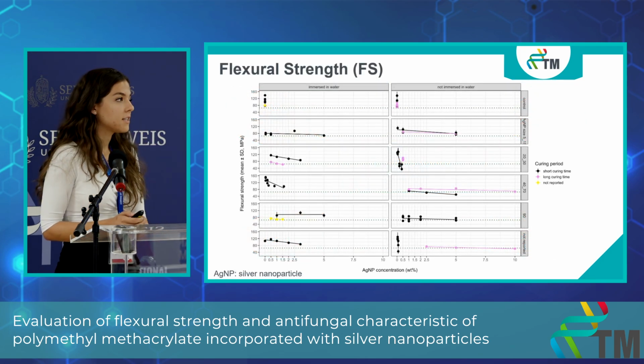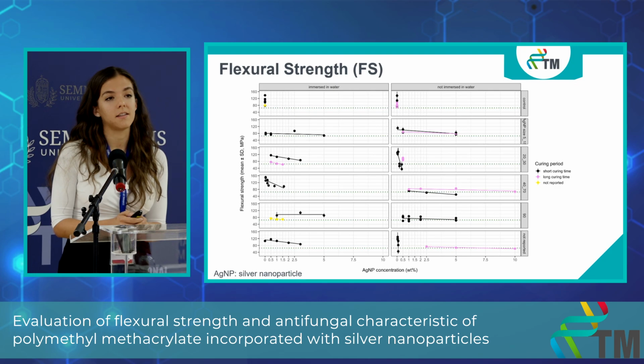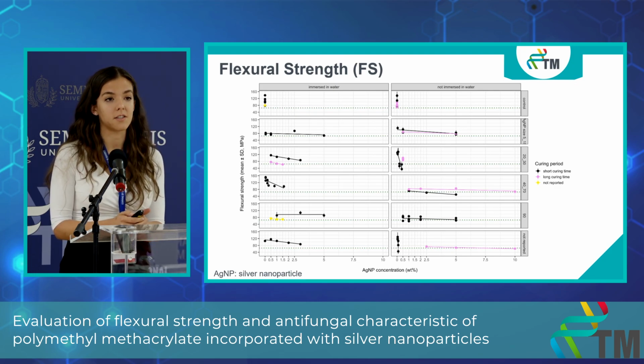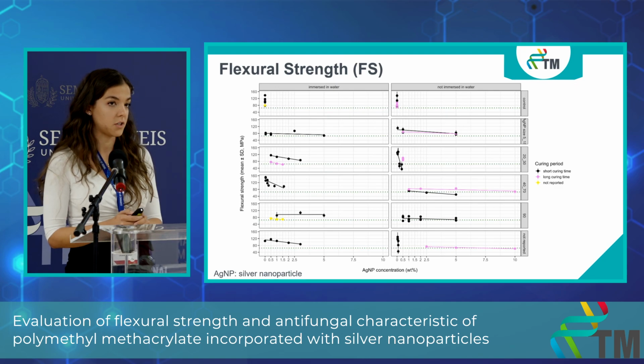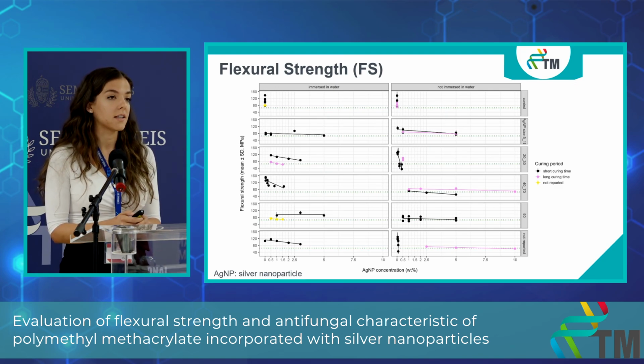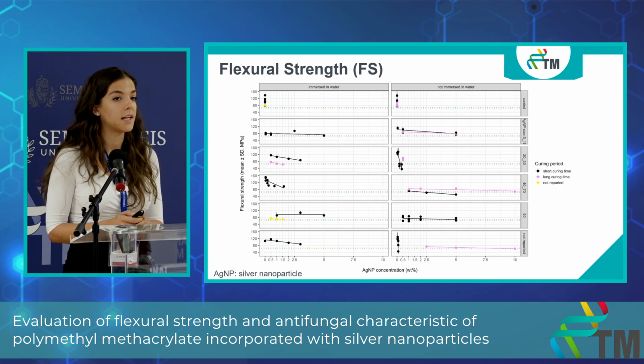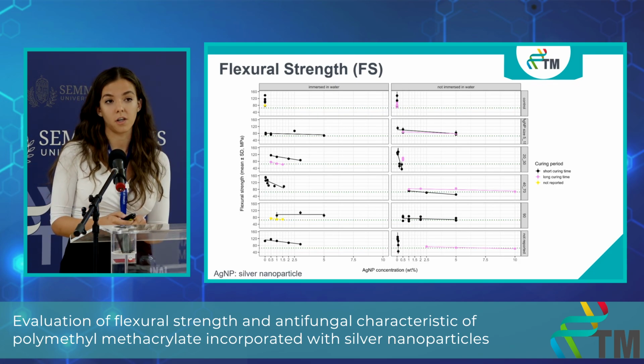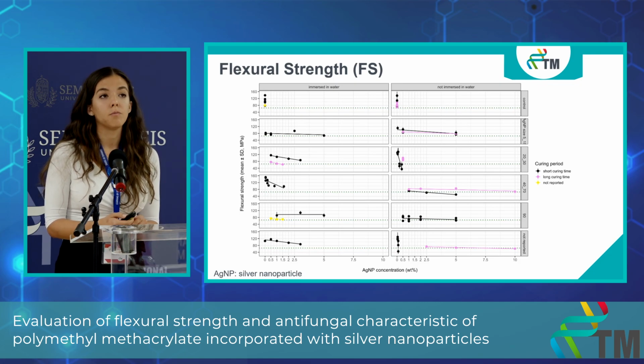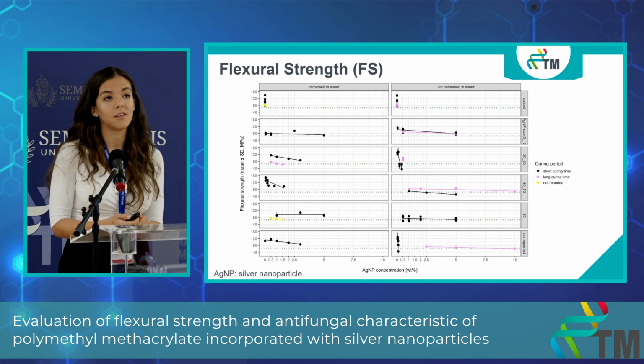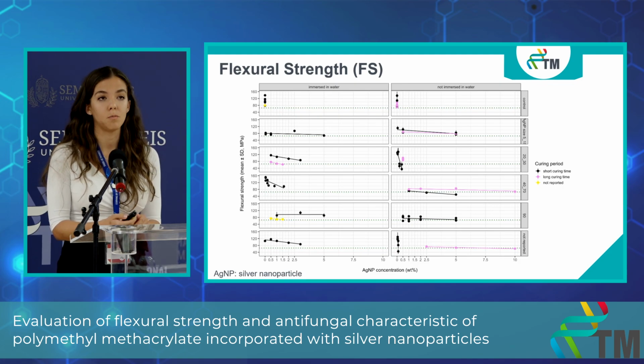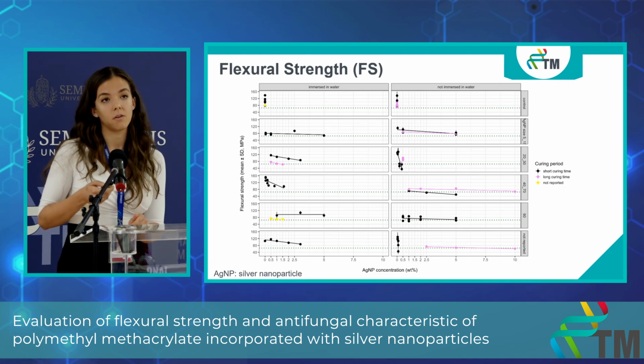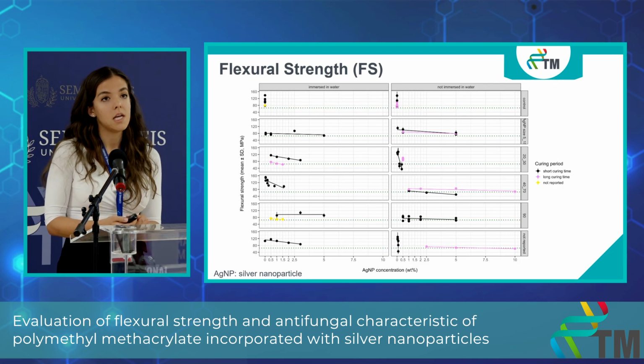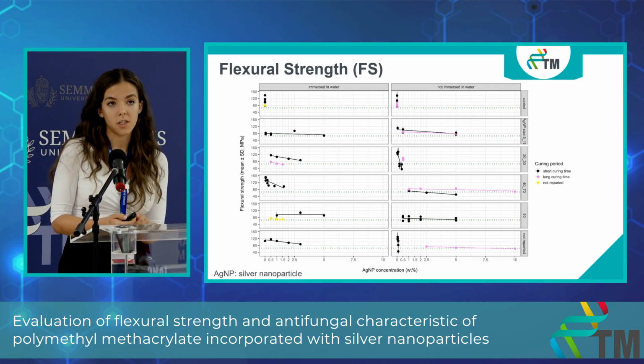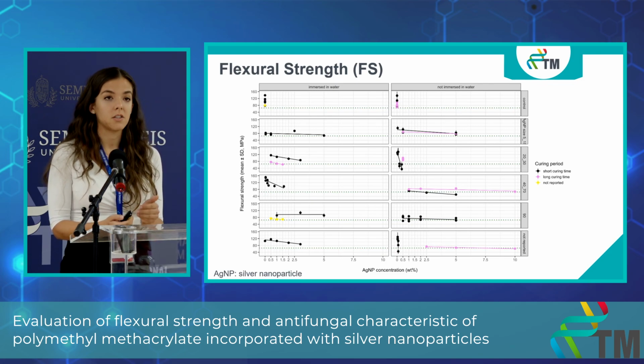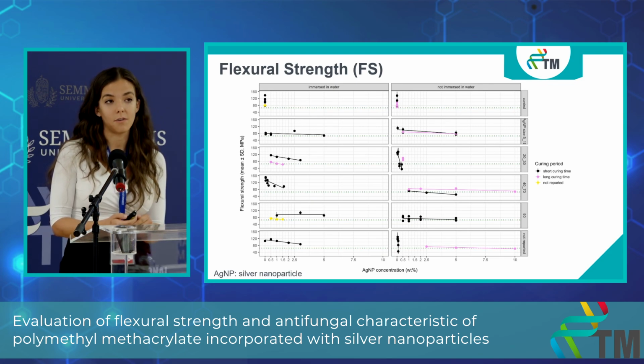You can see here the results of the flexural strengths, and this graph shows how the flexural strength changes as the silver nanoparticle concentration increases. On the vertical axis you can see the flexural strength in megapascal, and on the horizontal axis you can see the silver nanoparticle concentration. And we can see the other modifying factors like the immersion and non-immersion of the samples in the columns, and on the horizontal rows you can see the different size ranges. And also the curing period is shown by different colors.